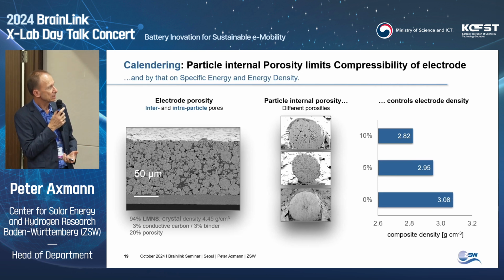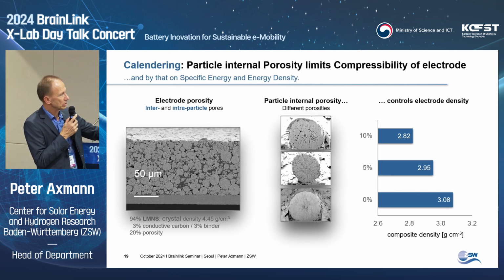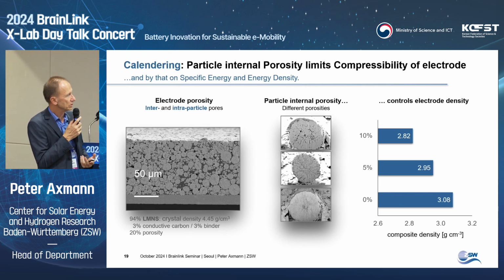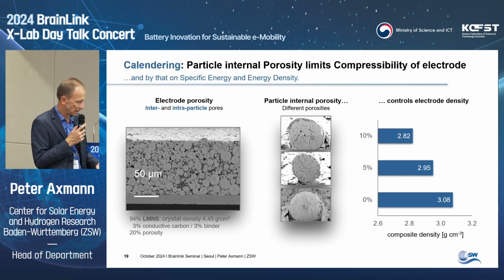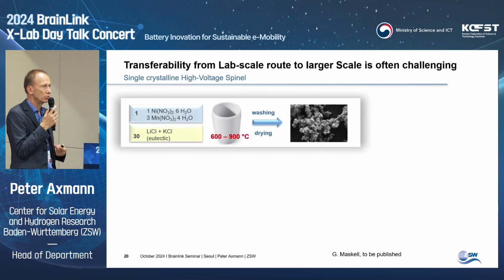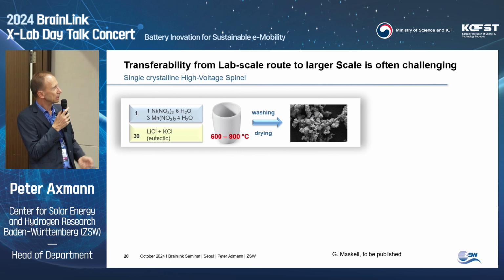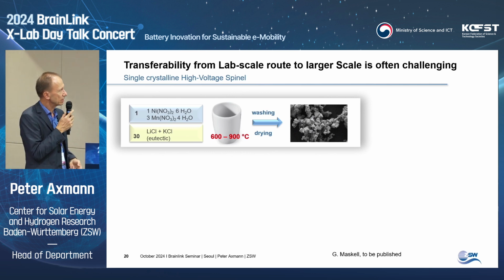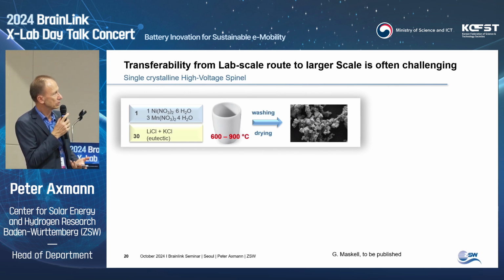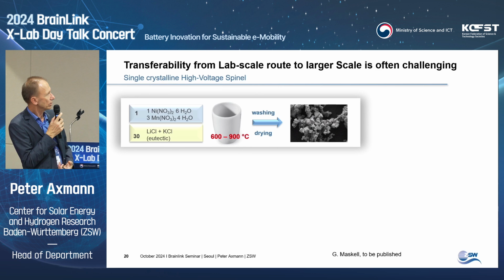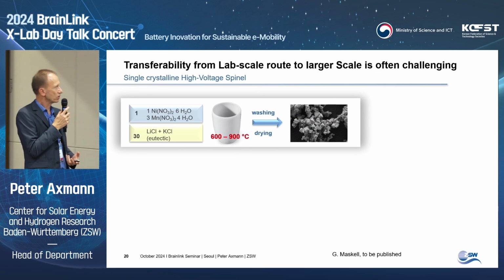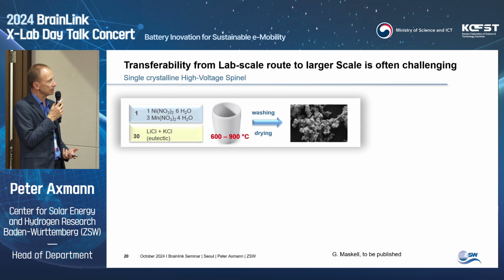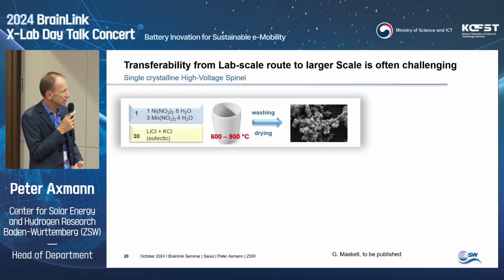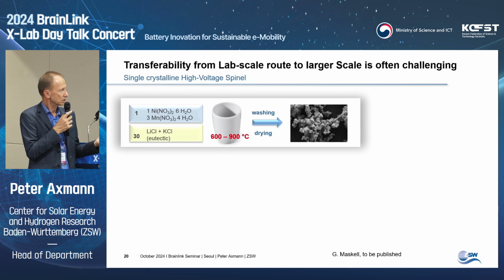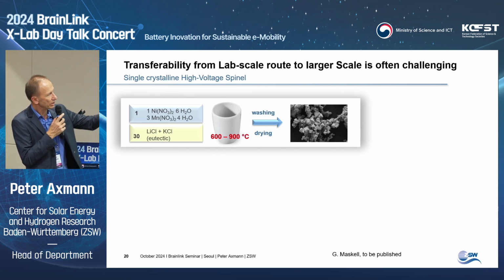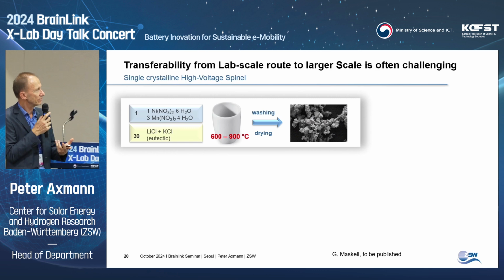So processing is influenced. But at this point, I want to step back in the lab. There are many lab materials made, and it's very important to have these materials made. But the step from the lab to a material which we can really coat on a larger scale is long. I just show it here for a single crystalline high voltage spinel. If we follow the typical recipes, you mix nitrates of the manganese and nickel compounds. You mix them with a 30-fold excess of a eutectic melt of lithium chloride, potassium chloride, heat it up to 900 degrees, let it cool down to a solid block. Then you wash it and dry it and end up with nicely shaped octahedra, which you can investigate.